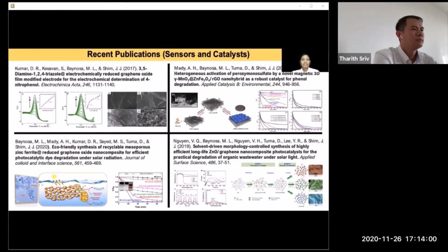So at this point, I would like to introduce to you some of our recent works on nanocomposites for the catalytic and photocatalytic degradation of organic pollutants in water. In the second paper on this slide, we synthesized a 3D heterostructure of gamma manganese dioxide, zinc ferrite, and reduced graphene oxide for the activation of peroxymonosulfate to produce sulfate radicals for the degradation of phenol. The synergistic effects of the combined materials resulted in high degradation rates of phenol using low catalyst dosage.